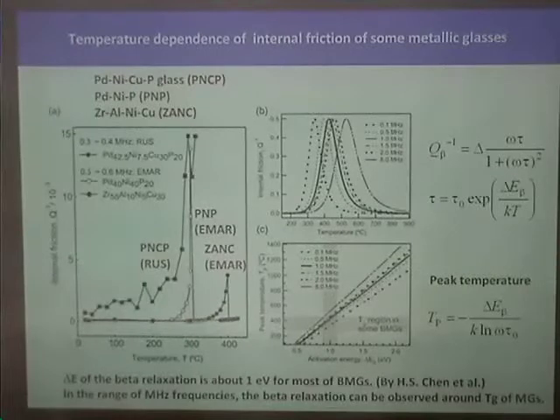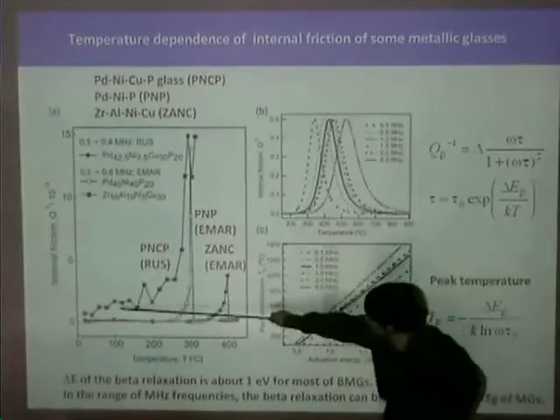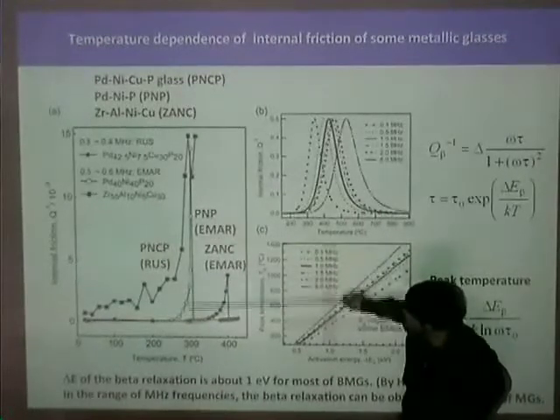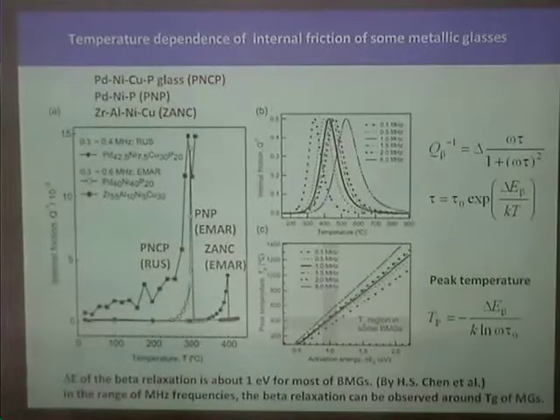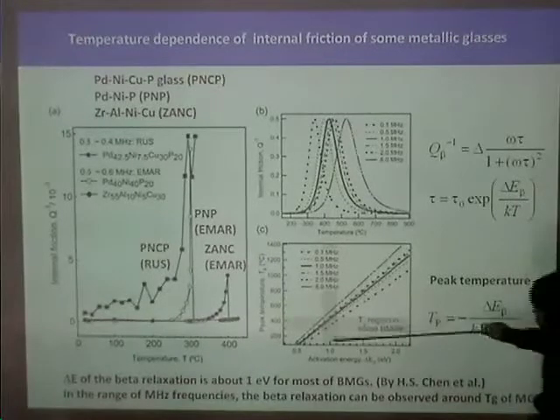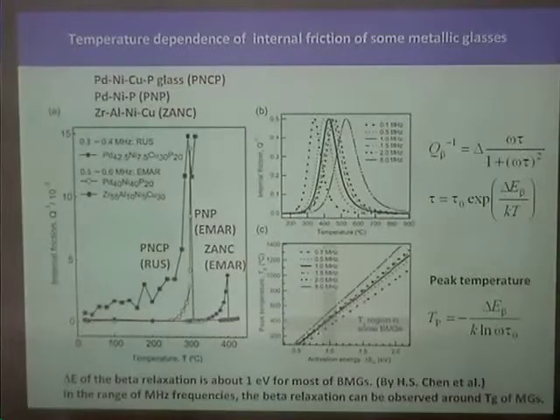So this is the summary of the three metallic glasses. Internal friction increases around the glass transition temperature, and then the crystallization occurs. When we assume that the beta relaxation activation energy is about 1 electron volt, the beta relaxation of the metallic glasses around the glass transition temperature is almost 1 megahertz. Therefore, under ultrasonic vibration in the 1 megahertz frequency range, the structure is very sensitive to the megahertz frequency range of ultrasonics.